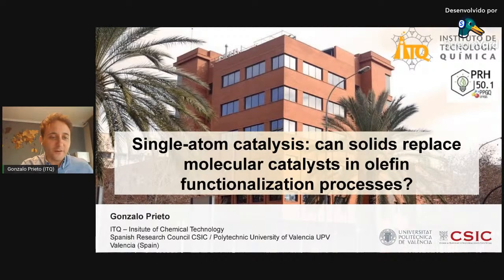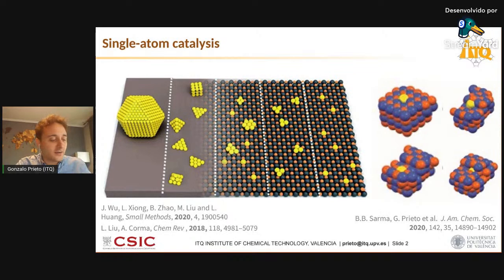So as I was saying, just a very brief intro to the concept of single atom catalysis. In single atom catalysis, the focus is on understanding the structural and catalytic properties of metals when they are supported, when they are dispersed on a support material, on a carrier material, to the limit of atomic dispersion. So going from the classical nanoparticles down to smaller metal clusters, a few atoms coordinated to each other, and all the way to the point where every single supported metal atom has no coordination to another atom of the same metal within the first at least two coordination shells. That's the limit of single atom dispersion, and that's where single atom catalysis focuses.